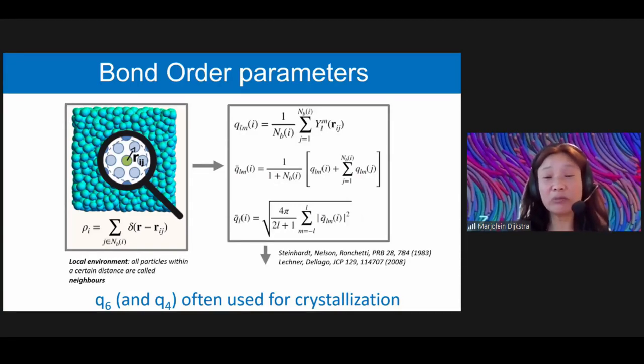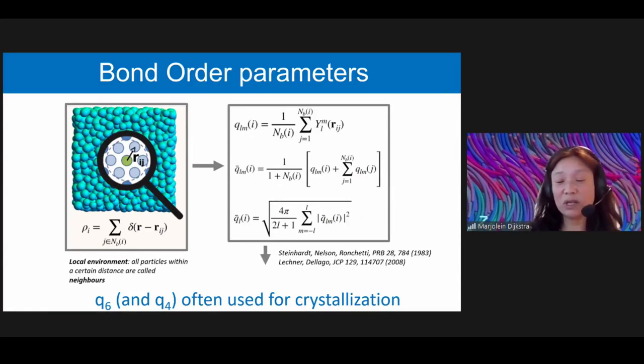And for all these neighbors, you then use the spherical harmonics, you calculate the Ylm for those particles, and you can sum over all the neighbors and get these qlm values. You can average over the next nearest shell, and you can make rotational invariance by just squaring these qlms or using a cubic rotational invariant of that. And often the q6 and the q4 bond order parameters are used to study crystallization because of the 6-fold and 4-fold symmetry in crystals.